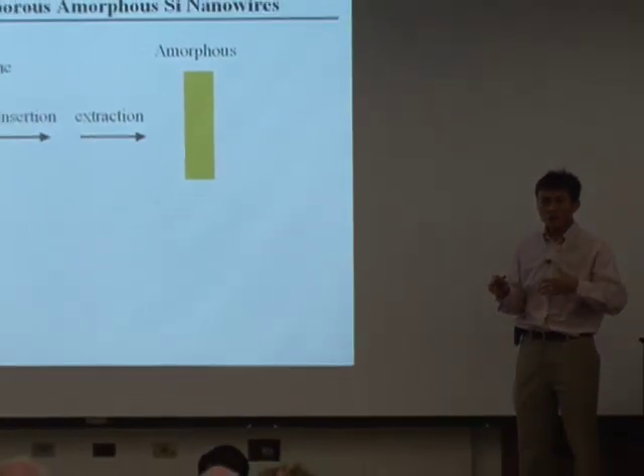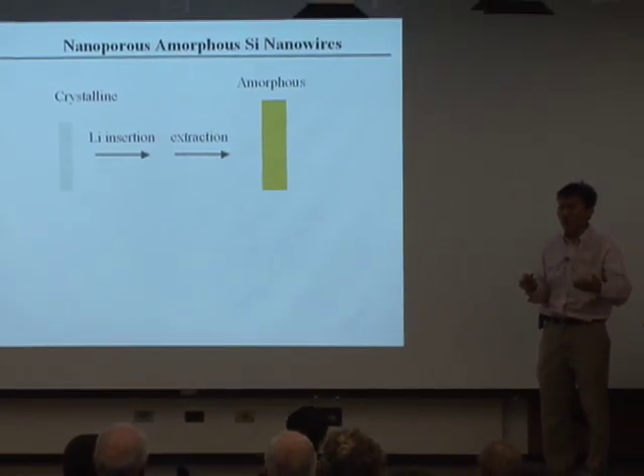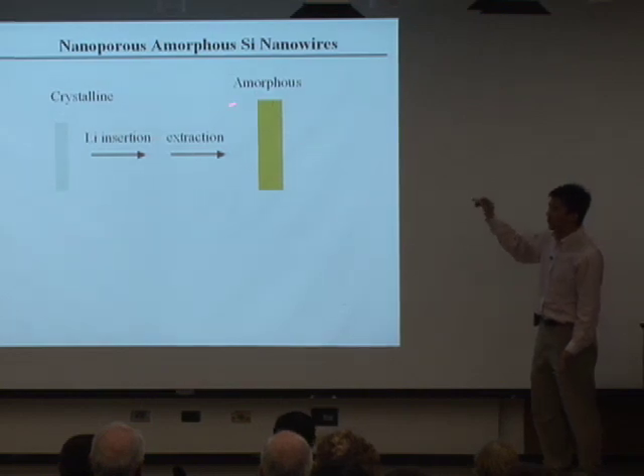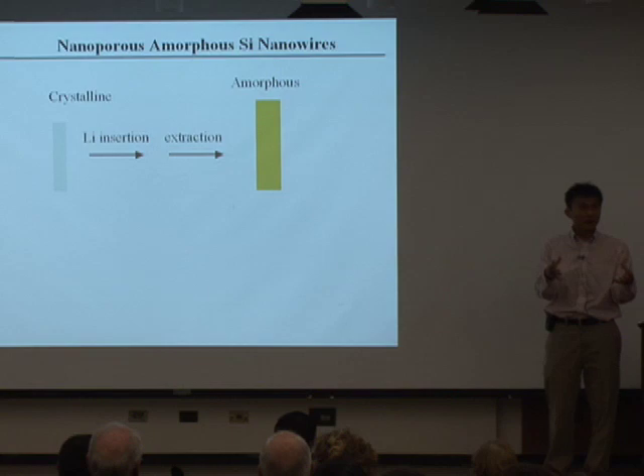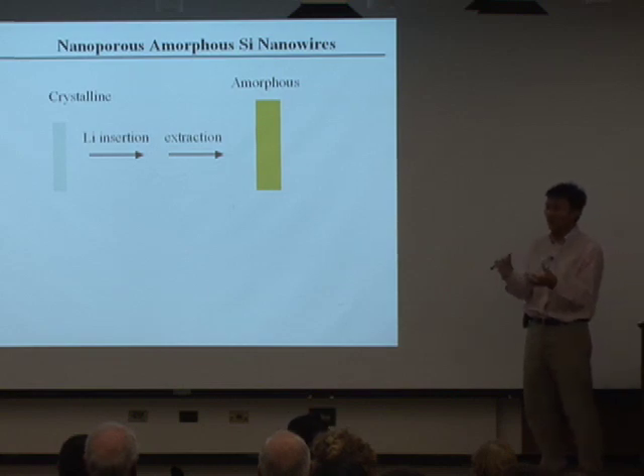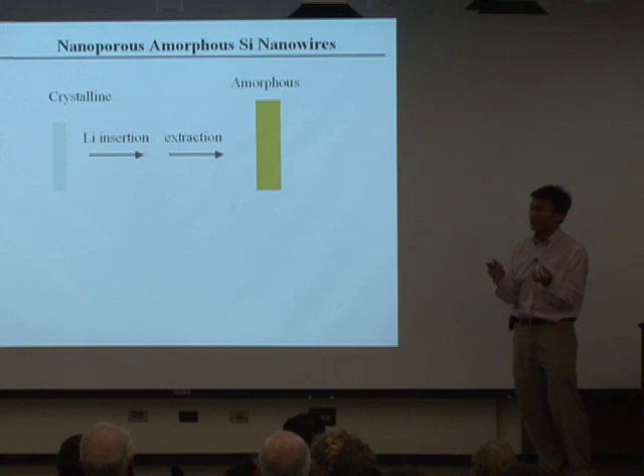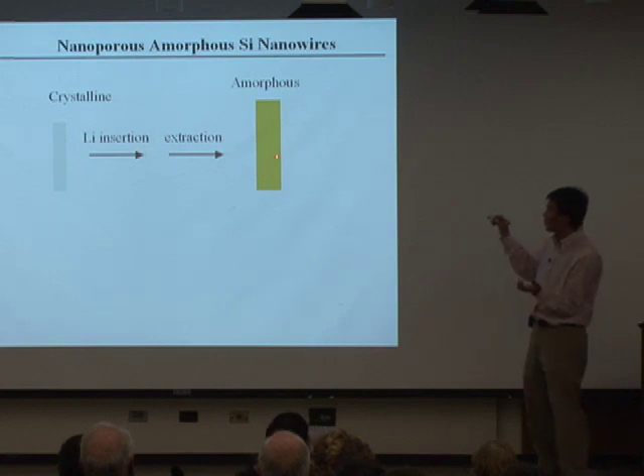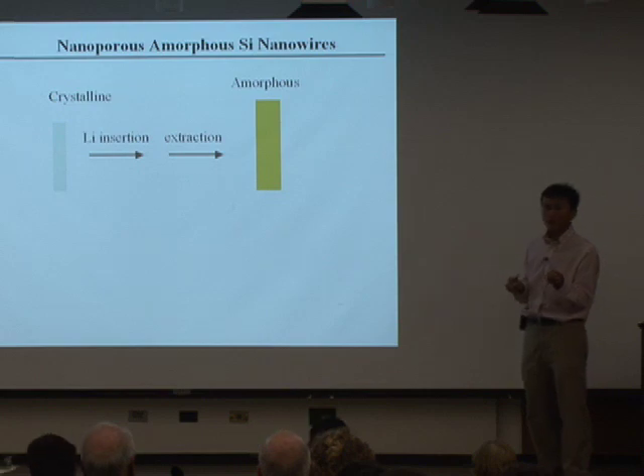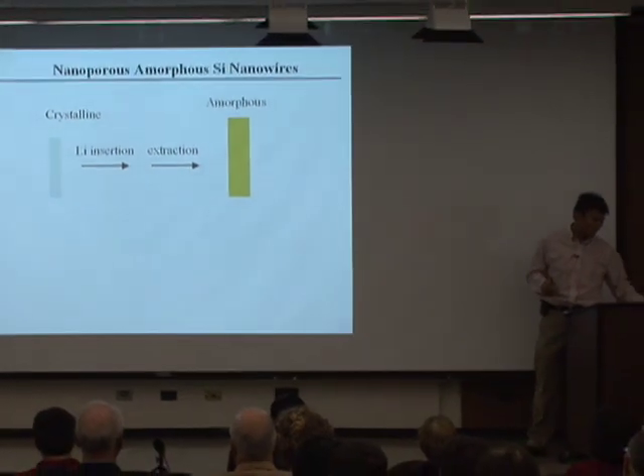Well, our research didn't stop right here. So when you look into what's happening in silicon nanowires, this is the overall picture. You take a crystalline silicon nanowire, you push lithium in, and it becomes amorphous. You take lithium out, it stays amorphous. So you're cycling your amorphous phase. This is your amorphous nanowire. They look bigger than your crystalline nanowires. So that allows you to think, is this only the amorphous phase? They look so much bigger than crystalline. There's got to be some nanopores inside.